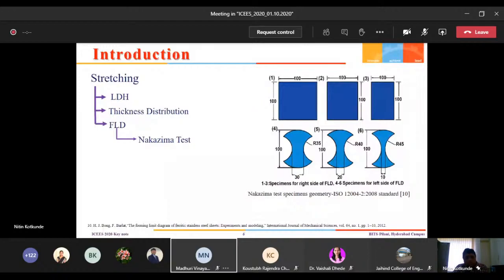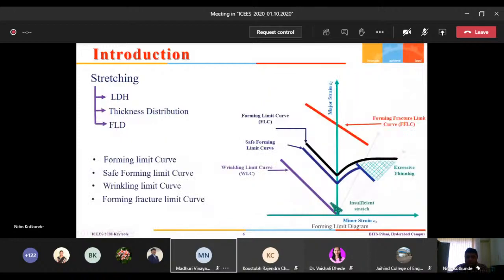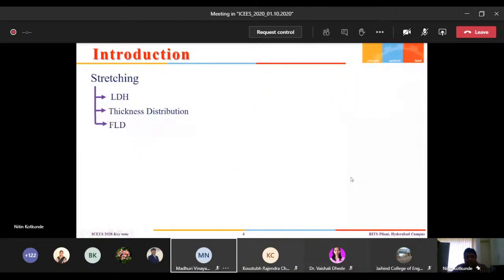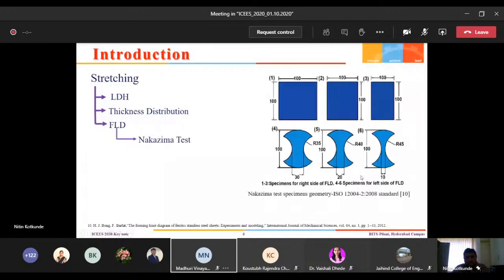The ISO standard 12004 we follow to do the Nakajima test. Usually the minimum number of specimens for the Nakajima test is 6. Specimens 1 to 3 are for the right side of the FLD. The right side points of an FLD we can get by using 1 to 3, and the left side points we get using the others.